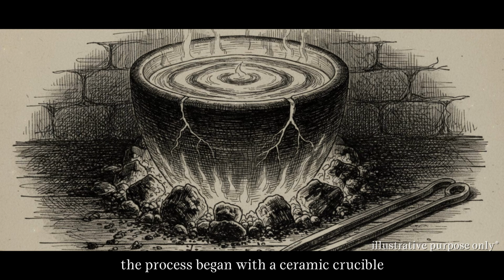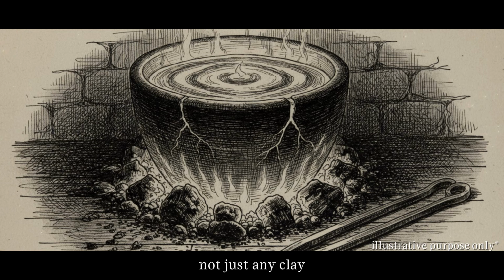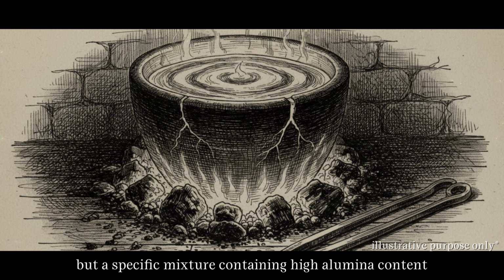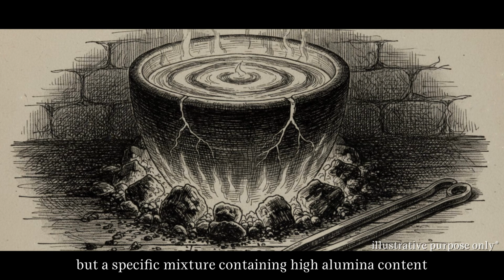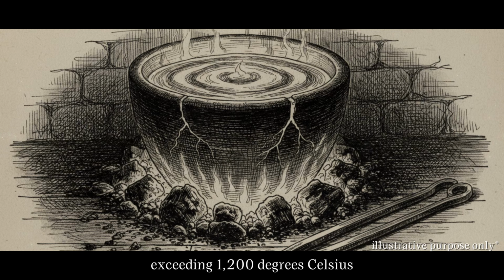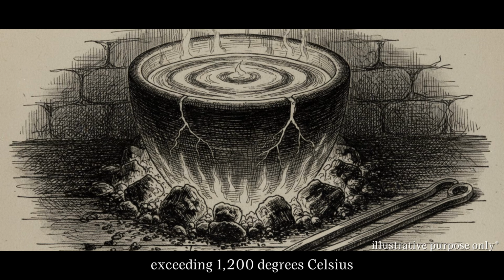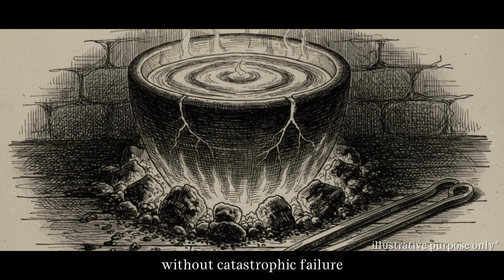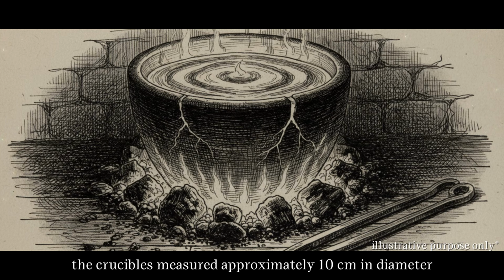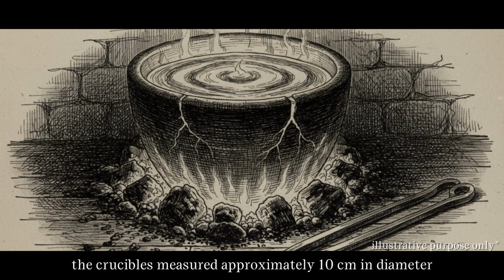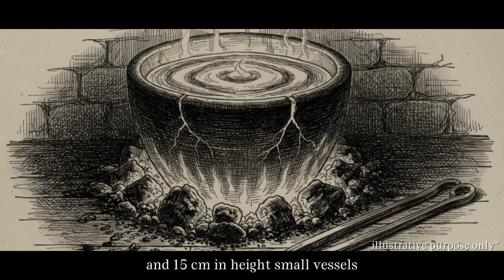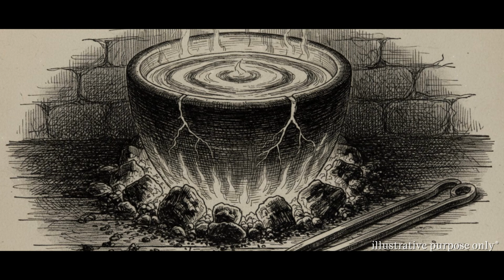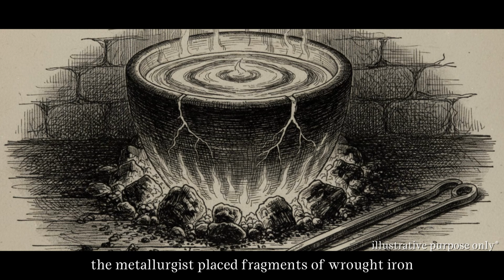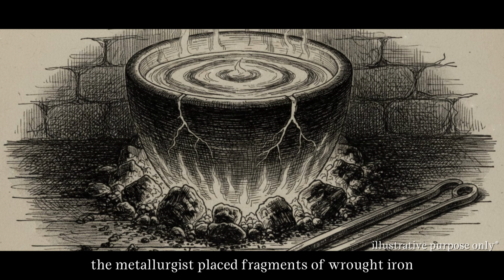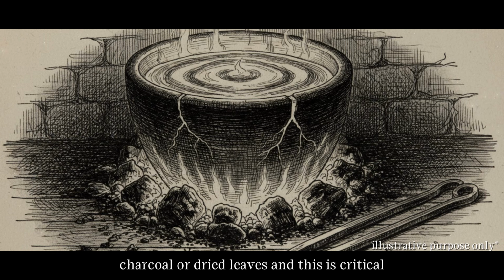I analyzed the production method by working backward from the archaeological evidence. The process began with a ceramic crucible, not just any clay, but a specific mixture containing high alumina content that could withstand temperatures exceeding 1,200 degrees Celsius without catastrophic failure. The crucibles measured approximately 10 centimeters in diameter and 15 centimeters in height. Small vessels. Batch production.